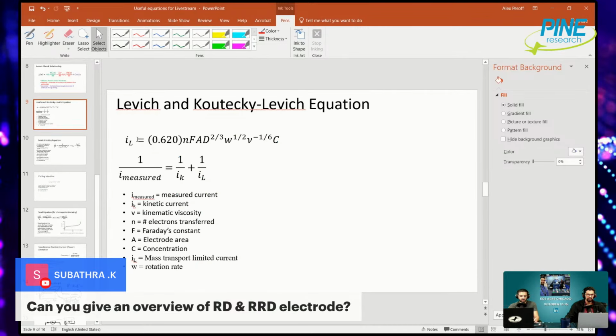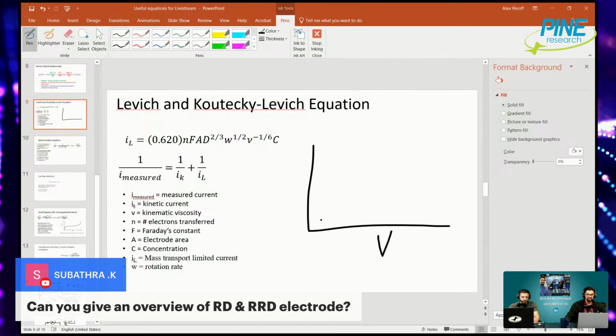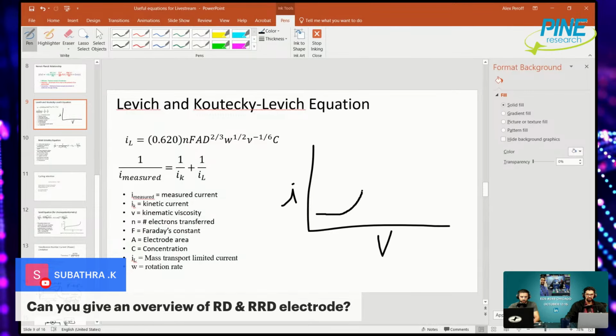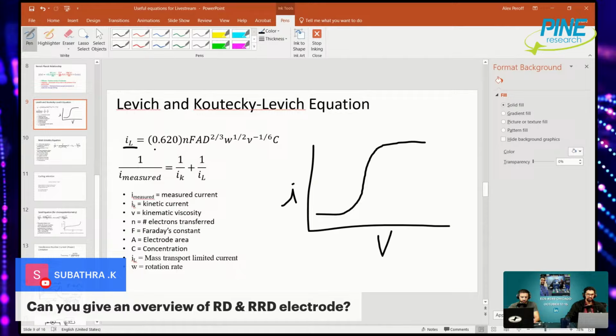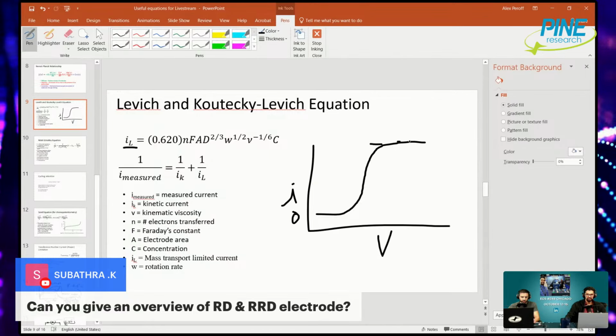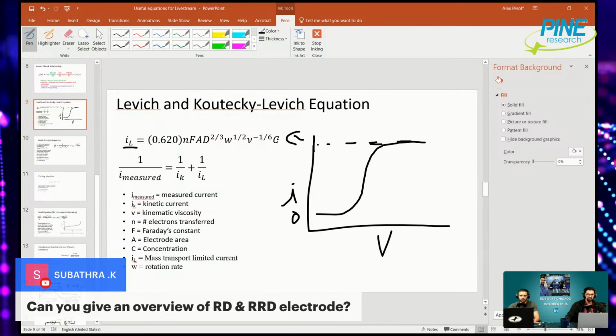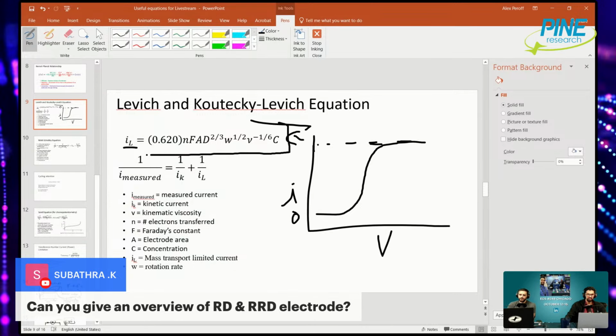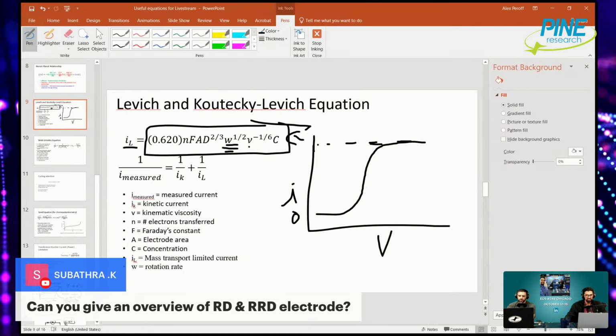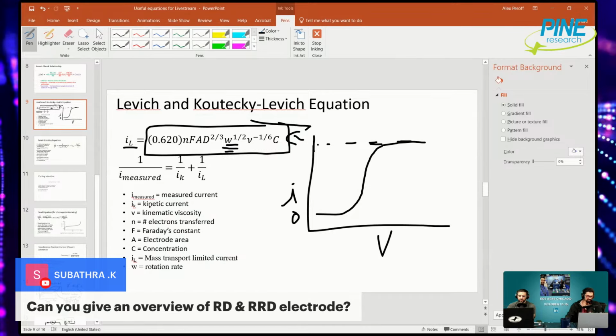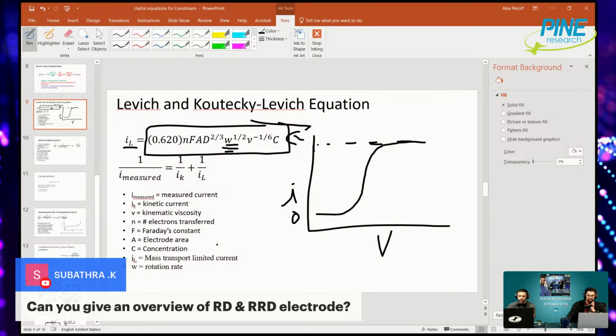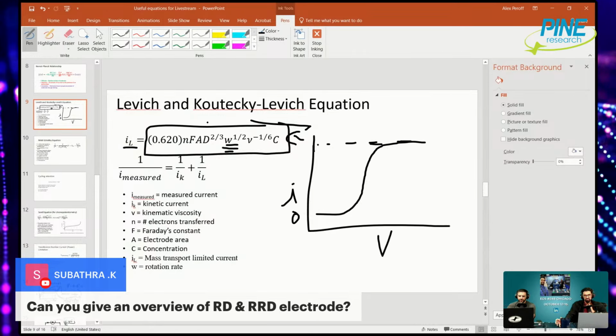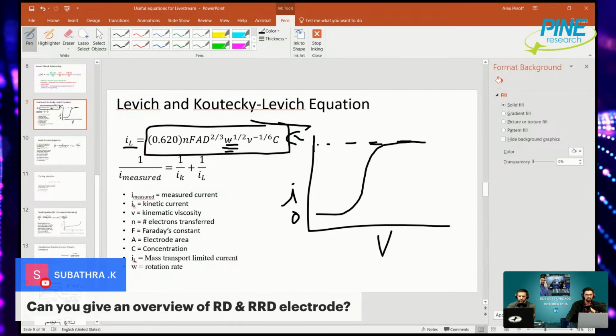They were able to create what's known as the Levich equation and the Koutecky-Levich equation, which describes, much like any cyclic voltammogram, these S-shaped voltammograms where the limiting current, let's say this is 0, and this is the limiting current. The limiting current is equal to this entire expression. And from this, you could change things like the rotation rate to calculate things like the diffusion coefficient and the kinematic viscosity, based on other parameters that are mostly constant. But this ended up becoming a very powerful electroanalytical chemistry technique because it allowed you to overcome mass transport.